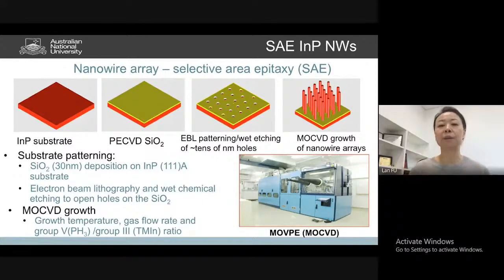Thereby they provide this gas precursor, and we heat the reactor to high temperature. Thereby we can decompose these 2 different precursors, providing group 3 indium and phosphorus, which epitaxially grow on your substrate. So that's the whole process. Of course, we need to optimize our growth parameters, very important parameters: growth temperature, the gas flow rate, and the group 5 to group 3 precursor ratio, because that will determine how good the crystalline quality of the material is, as you will see later on.